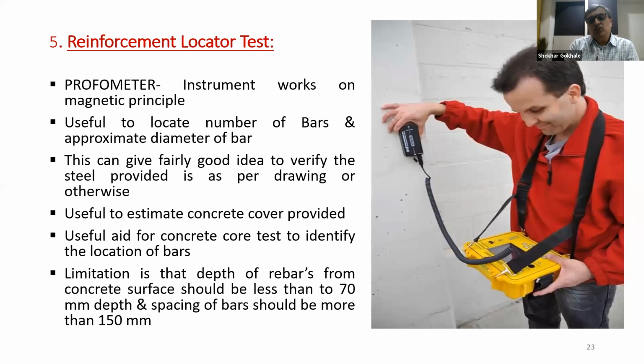And this test is also useful before the core test is conducted, because to extract the core from the member, we need to locate the reinforcement bars inside the member, so that while extracting the core, the reinforcement bar is not damaged. The only limitation is that the depth of rebars from the concrete surface should not be more than 70 mm, and the spacing of bars should be more than 150 mm. Then only can this test be conducted.